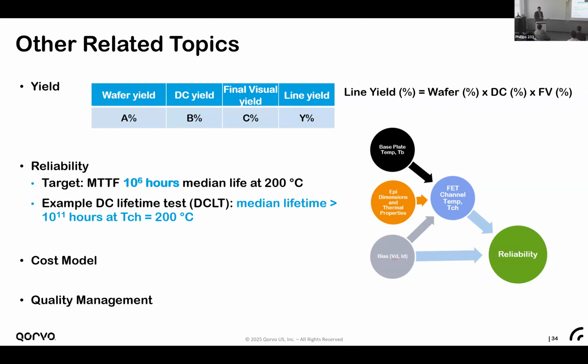And the reliability, as I mentioned, we need our device to survive for 10 to the power 6 hours at 200 degrees C channel temperature. This is a very stringent condition, but sometimes we will get a good surprise. For example, for some of our 90 nanometer gate devices, the lifetime is much longer.